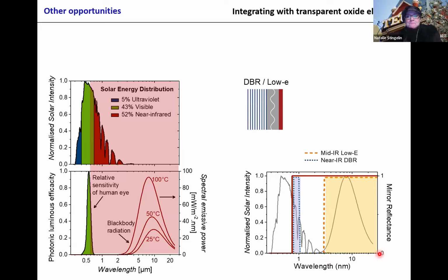If we would use a simple mirror like we showed at the beginning, the DBR with the same thicknesses, we could already get quite a bit of the near infrared reflected. But you see we would still have here a lot of the near to mid infrared that is there.